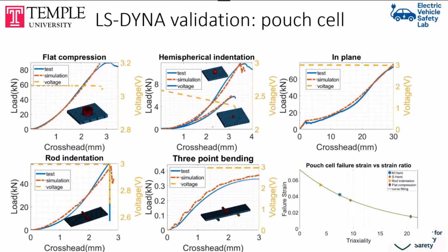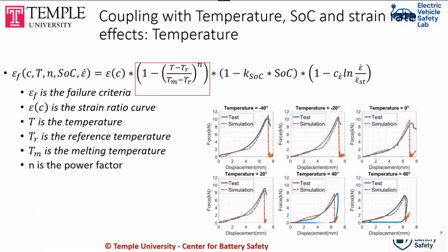You need to make sure that element orientations are correct, otherwise the result will be messy, and it's not my fault or LS-DYNA's fault. I know the manual doesn't explain it in too much detail, but the main thing for the model to work fine is that the element orientations should be aligned with the layers of the component in the cell. Now, the most recent update: the base model I told you about was for room temperature, for zero state of charge, and for quasi-static loading.